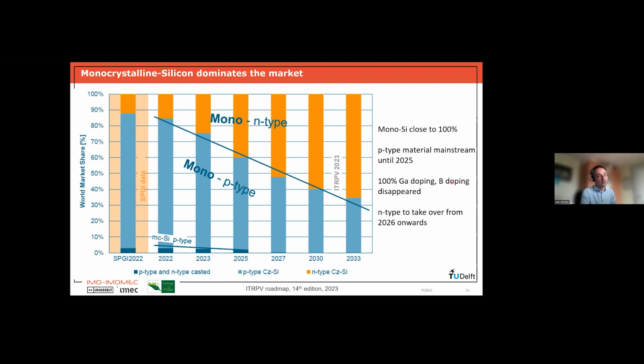And finally also interesting to know, that's also changed in a very short time span. So if you look at these P-type monosilicon wafers, they are doped P-type by using gallium. So until 5 years ago, almost all wafers were doped by using boron. But if you use boron, we know that already for a long time, you have sometimes the possibility that you introduce so-called boron-oxygen complexes. This is a type of defect that can actually degrade a little bit your solar cell. It degrades the efficiency. And to avoid that, because we really want to have stable, high-efficiency solar cells, we now actually use gallium, which does not have this problem. So it is another example how the industry can very quickly completely change from one material to the other material to solve somehow a problem and to actually get a little bit cheaper or a little bit higher in efficiency.